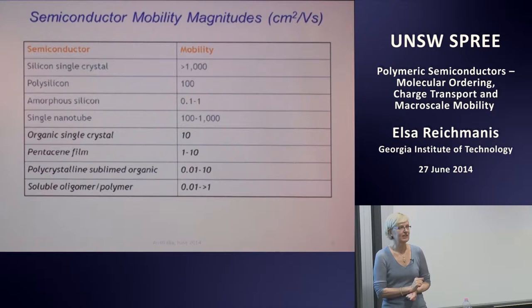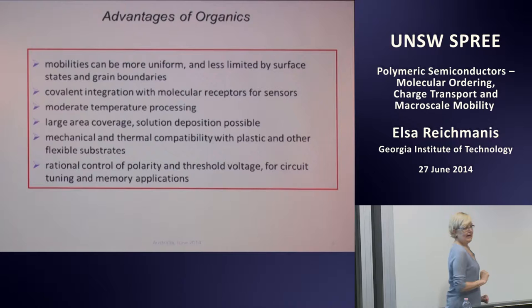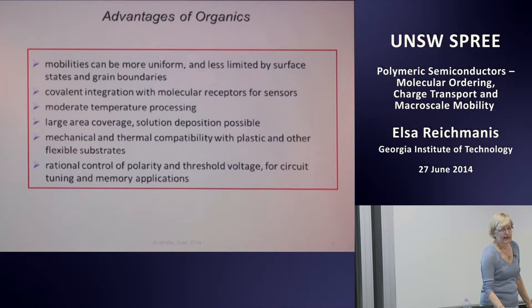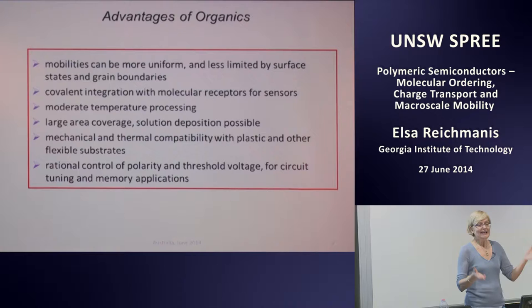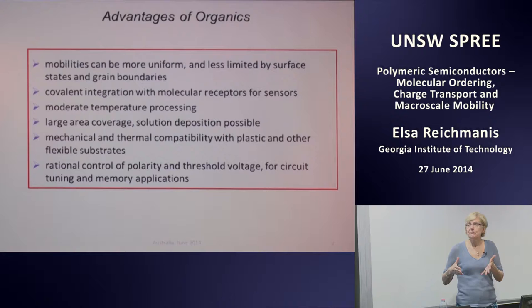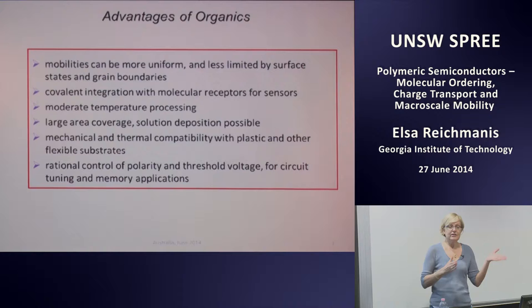All right, so there are advantages to the organics, and this summarizes what those advantages could be. The mobilities could be a little more uniform, less limited by surface states. Grain boundaries may not be as big of an issue, but as you'll see later on in my presentation, they kind of are an issue. One could think about covalently integrating a molecular receptor into the semiconducting active layer as a receptor for some sensor application, maybe a biomedical sensor application. The processing is going to be done at a lower temperature, so it's going to be more moderate. Less energy would be used.